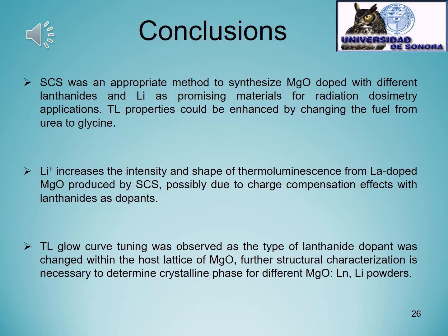Another conclusion is that lithium, or the lithium ion, increases the intensity and shape of thermoluminescence in the case of lanthanide-doped magnesium oxide produced by SCS, possibly due to charge compensation effects with lanthanides as dopants. This effect we observed before in the case of cerium and lithium doped magnesium oxide.